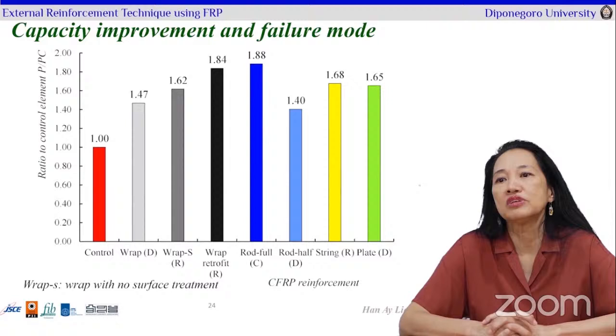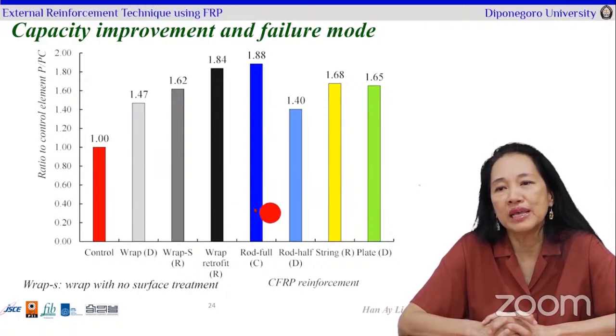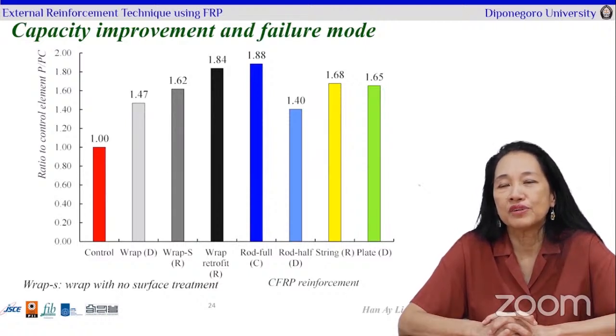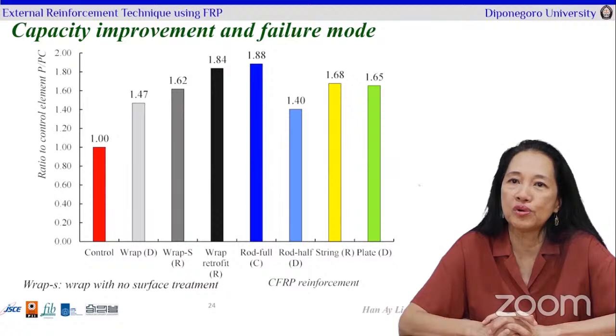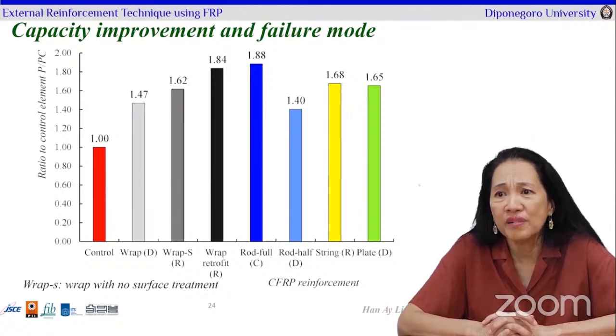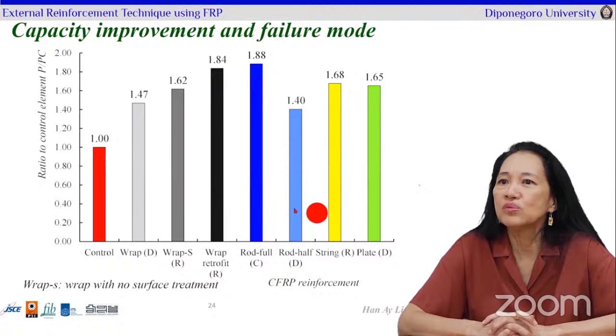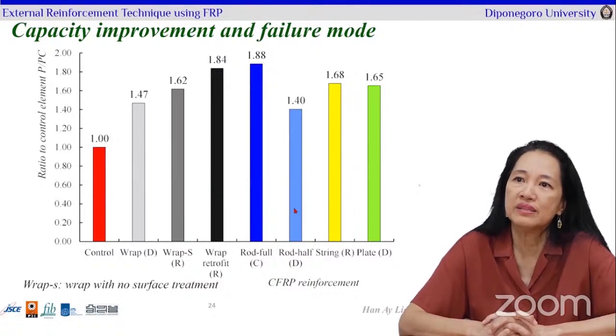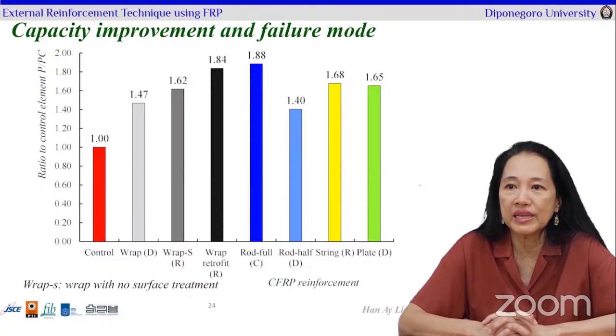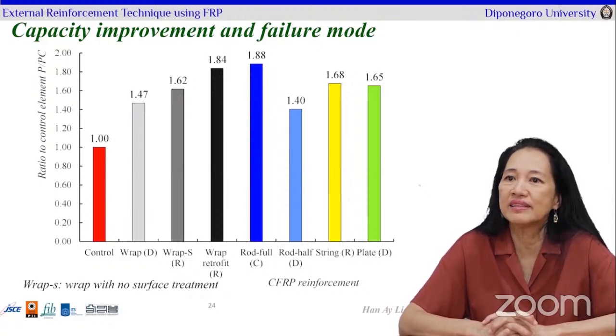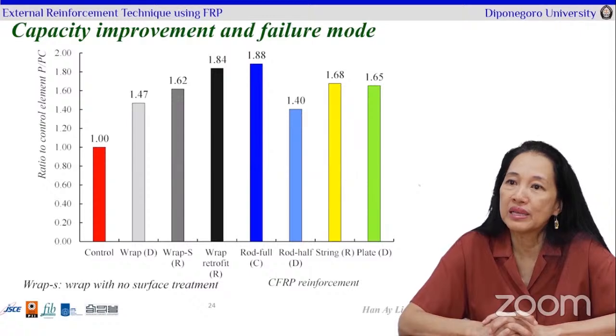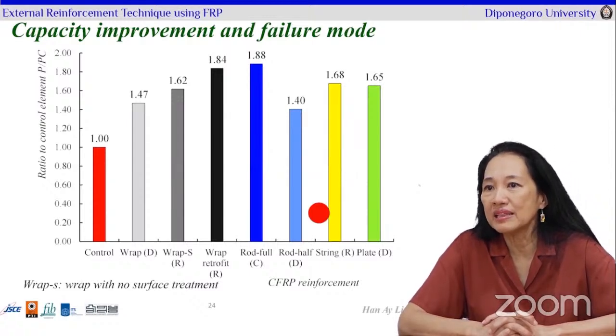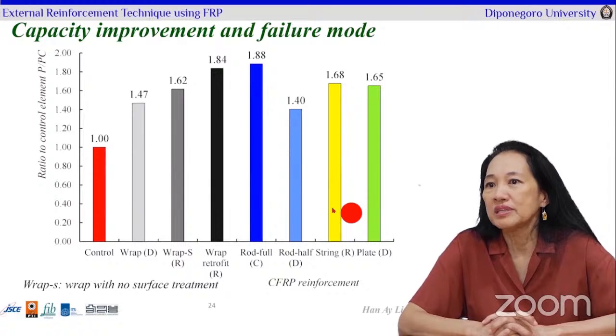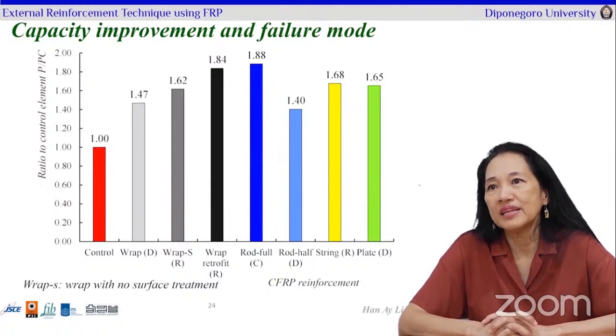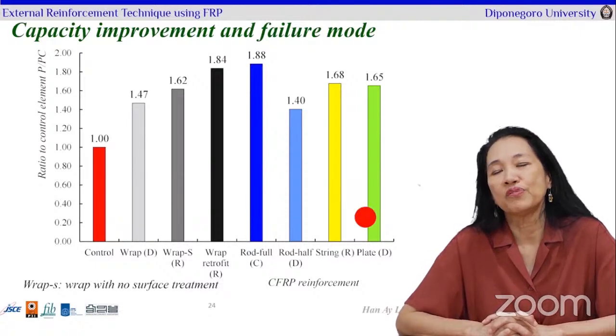The best one, of course, is the rod, which was fully embedded according to the ACI 440. That will have an increase of 88% to the normal beam. The half embedded rod still was good enough for a 40%, but this one resulted in debonding. That's why a D is designated for the failure mode. And the string and the plate, which ruptured and debonded, had an increase of 68 and 65%.